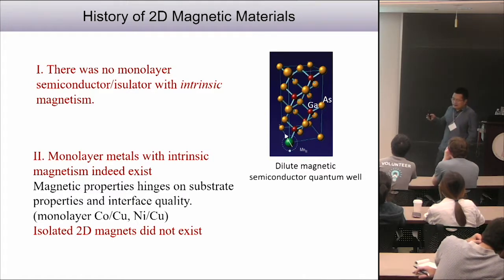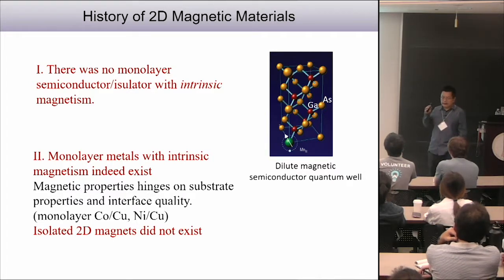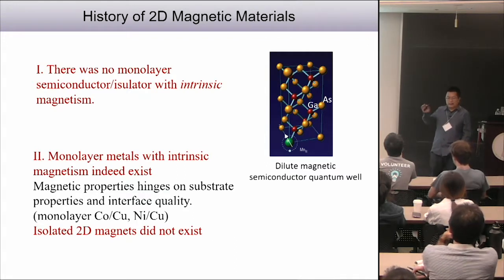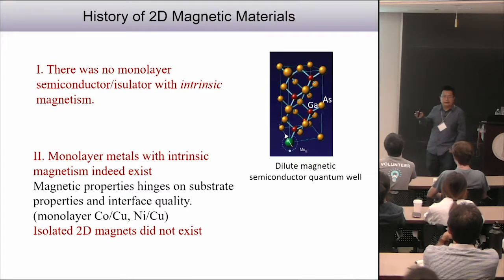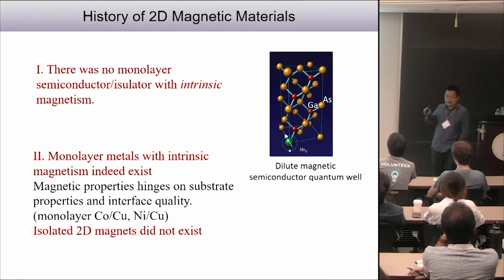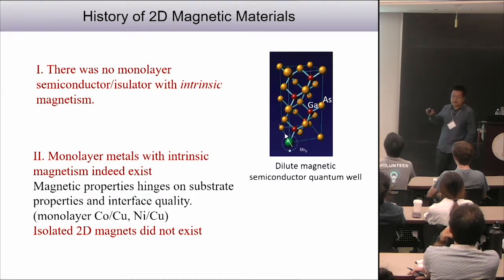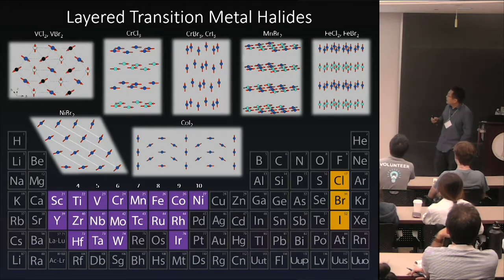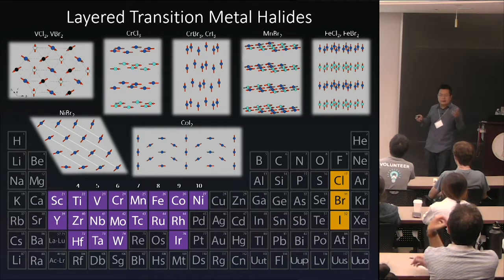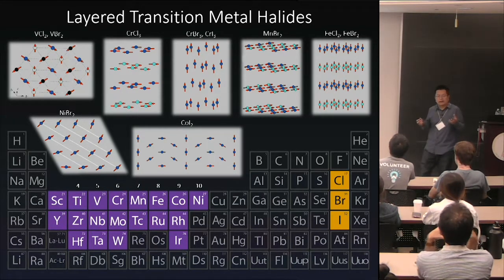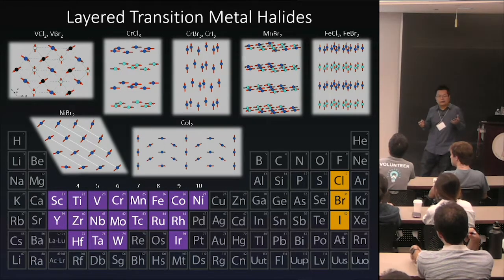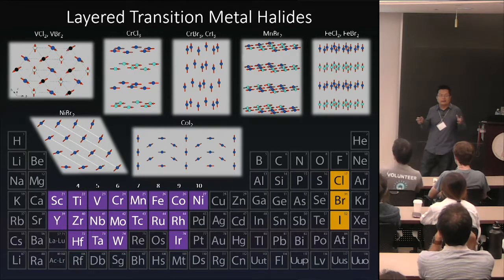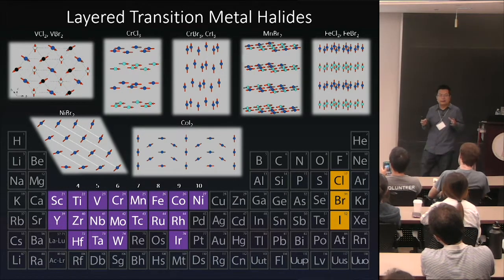The challenge I saw is that in the past, when you try to get these two-dimensional magnets, they usually use sputtering or MBE. Those are challenging techniques to go really thin, because even with MBE you can get to monolayer, but you cannot grow just any material — the substrate is really important for epitaxial matching. But now we know with van der Waals crystals — if you can find a van der Waals magnet and exfoliate it into monolayer — there's a chance. Not every van der Waals crystal can be exfoliated, so you have to be very lucky.